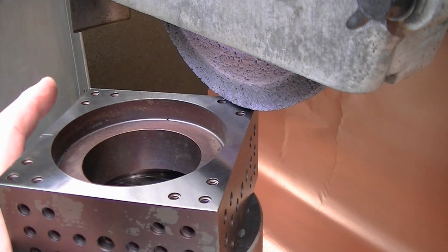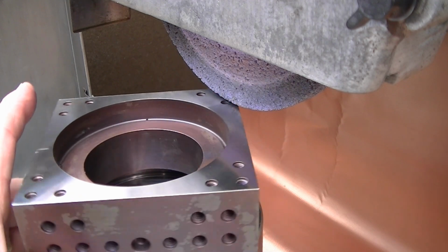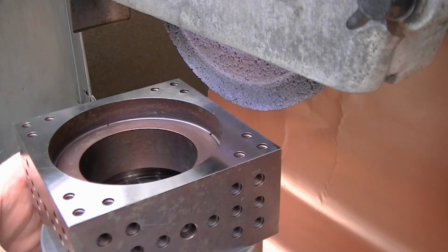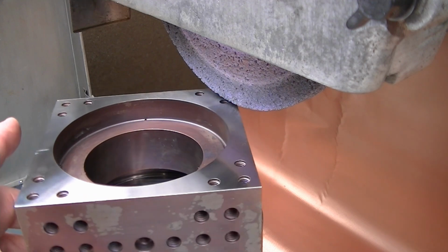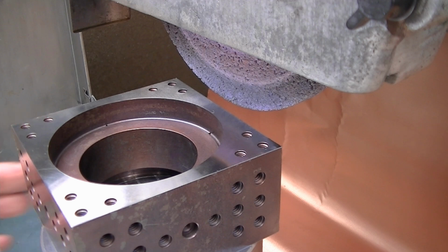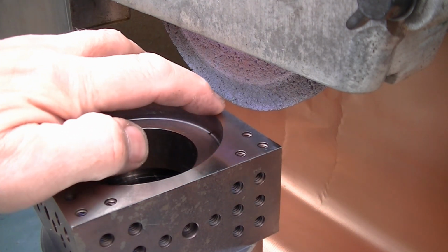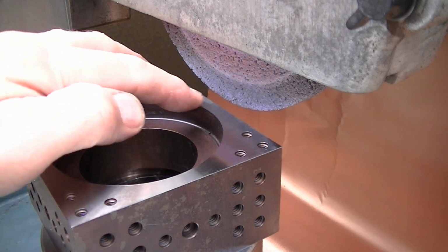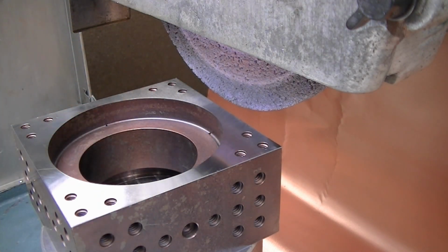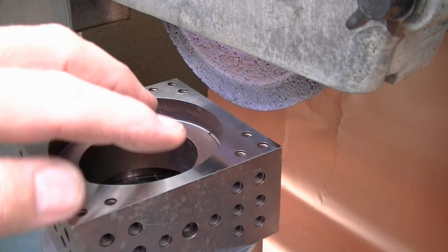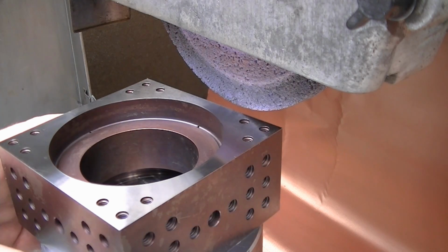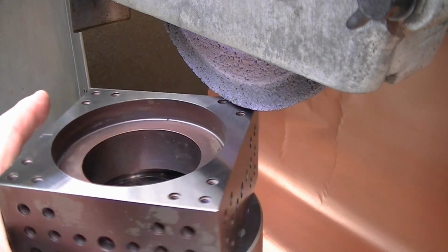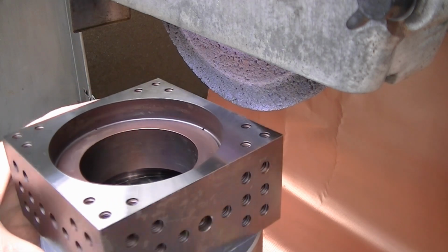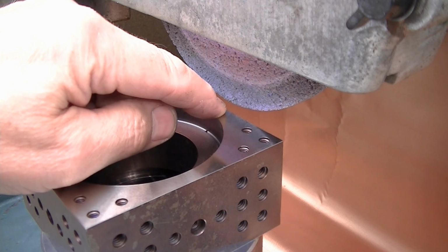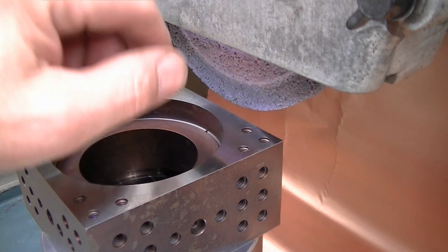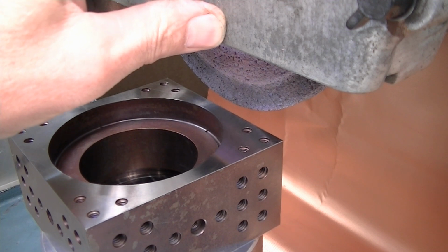And I'm bringing that up because in any grinding, and this rotary setup just points out a situation where it's easy to get a good example to explain a phenomenon. When the grinding wheel is engaged here, it's got a continuous bearing, meaning it's engaged with the part and it's actually pushing on the part, trying to cut continuously. And when it moves out here, where it's off the part, but it engages intermittently, 4 times per revolution in this case, it climbs up onto the part. You have a situation where here it's loaded continuously, but here, as it comes off the part, this can actually unload and drop because it's not sprung.